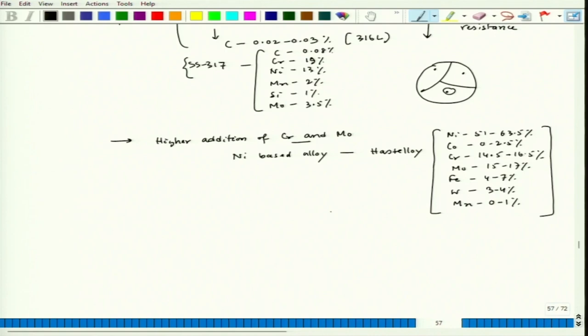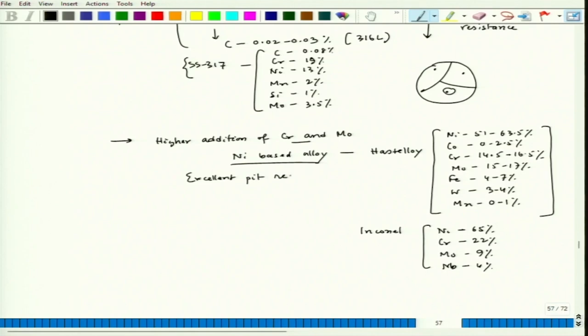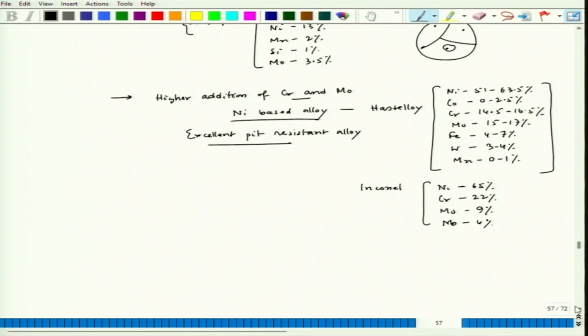Okay, we can also use Inconel. So there we have a little less molybdenum, but the chromium content goes up. So there, nickel is of the level of 65%, chromium of the level of 22%, molybdenum 9%, and there could be presence of niobium about 4%. So you could see that cost wise these two are extremely costly, but they can offer extremely high pitting resistance. So this is an excellent pit resistant alloy. Okay, that's what in pump systems can be made of nickel based alloys in chloride medium.